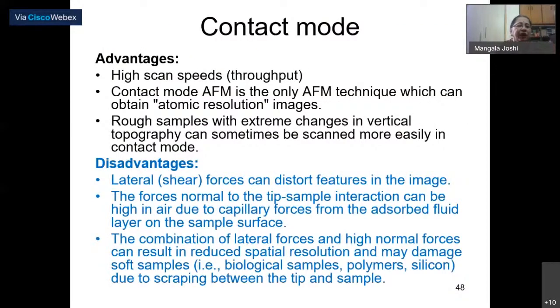So the contact mode, the advantages are high scan speeds, throughput is possible. Contact mode AFM is the only AFM technique which can obtain atomic resolution images. Rough samples with extreme changes in vertical topography can sometimes be scanned more easily in contact mode. So disadvantages are that the lateral shear forces can distort the features in the image. The forces normal to the tip sample interaction can be high in air due to capillary forces from the adsorbed fluid layer on the sample surface. Then the combination of lateral forces and high normal forces can result in reduced spatial resolution and may damage soft samples, especially biological samples or soft polymers or silicon. So these are the advantages and disadvantages of the contact mode. Next.